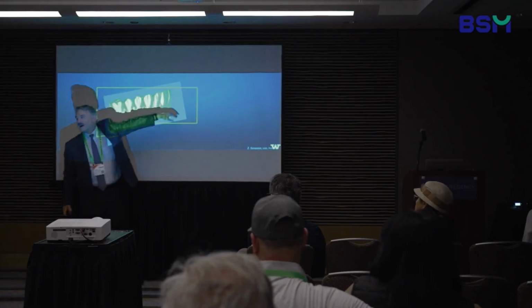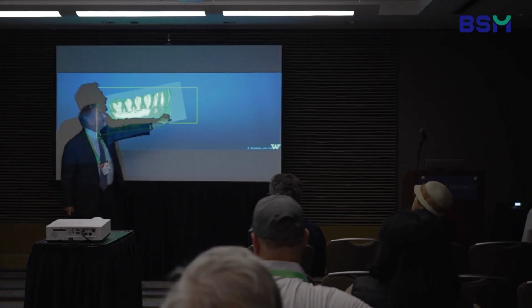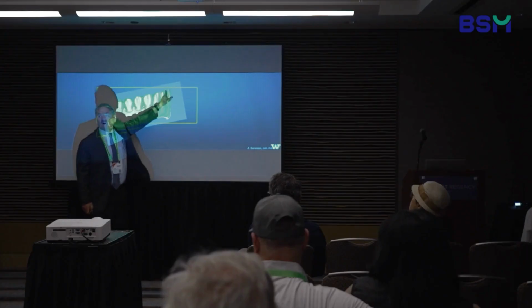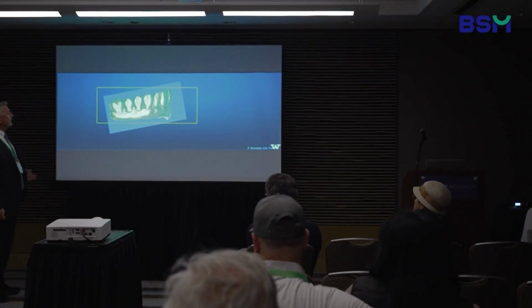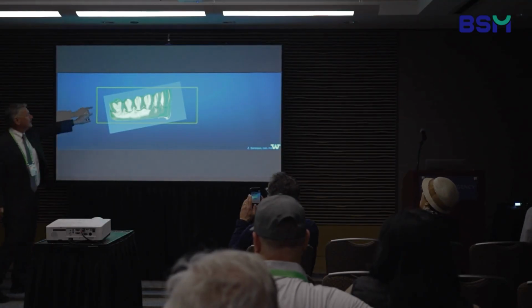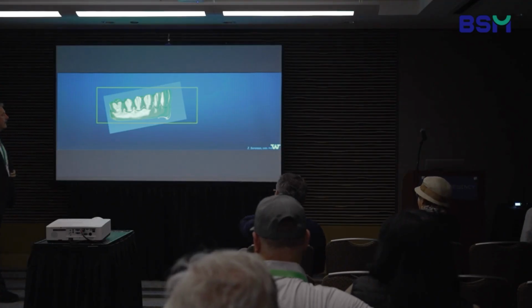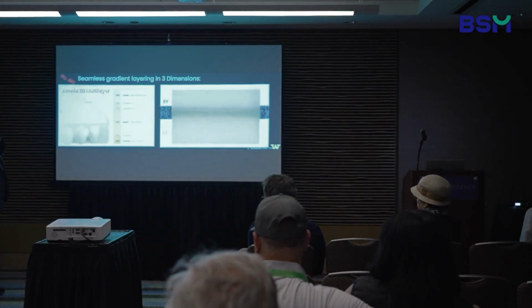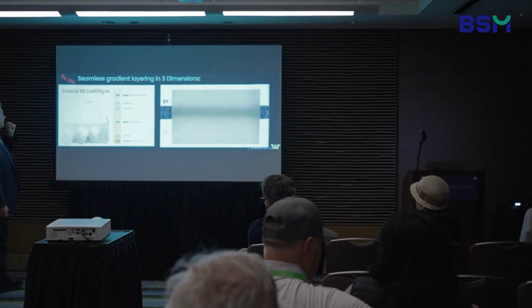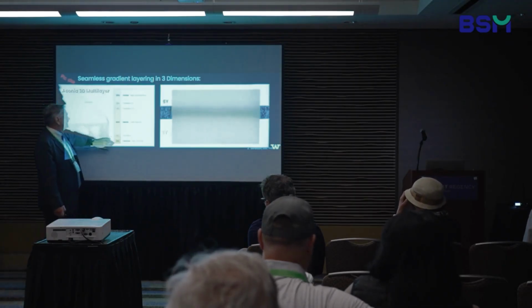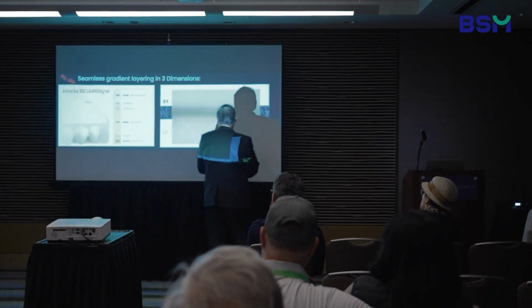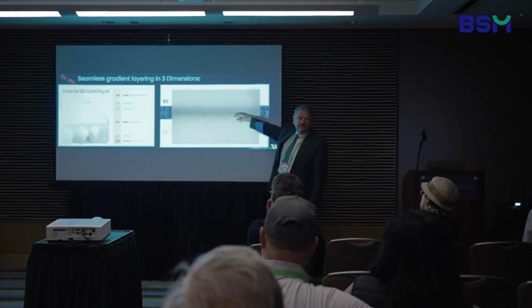But up here, again, where I have only 1/3 the biting force, then I can have more of the 5Y in that and create those aesthetics. So I just want you to think about it, no matter what system you're using, to consider how you nest those bridges into the disc. So, all right, here's the Aconia 3D multi-layer material or master material, and what they do is they've got 6 layers in here, and with the technology and the application process, they're able to also create a seamless or natural gradient transformation within those levels.